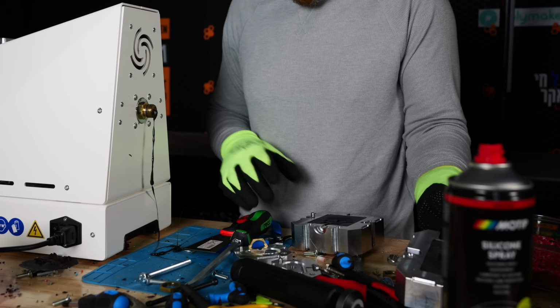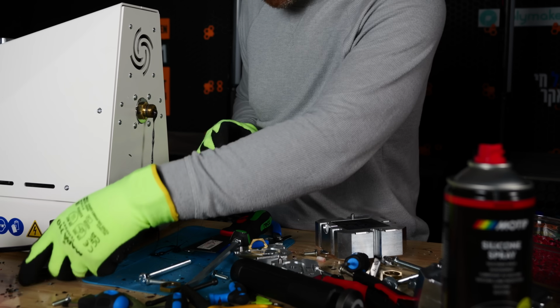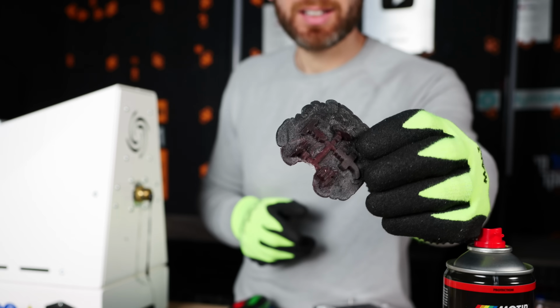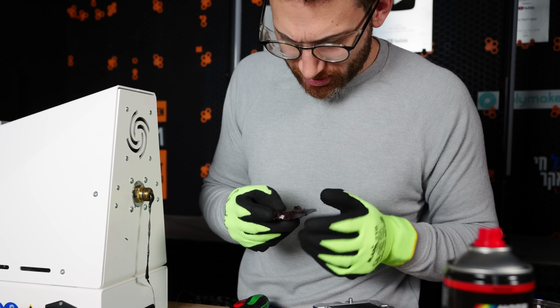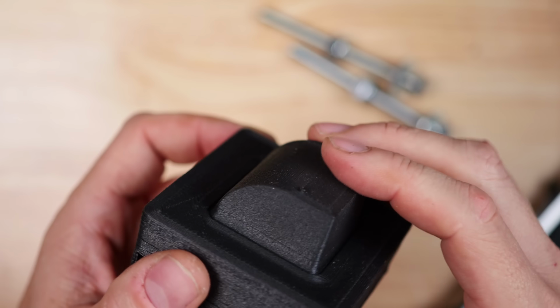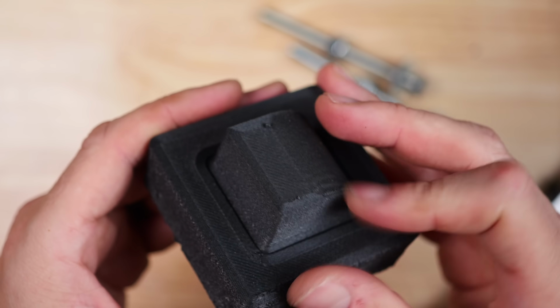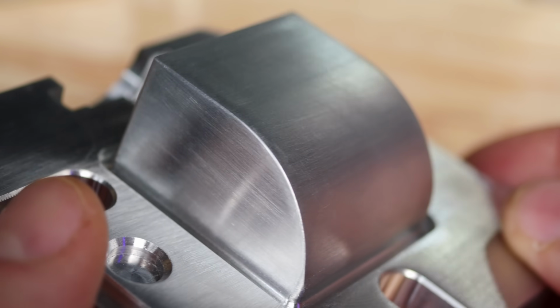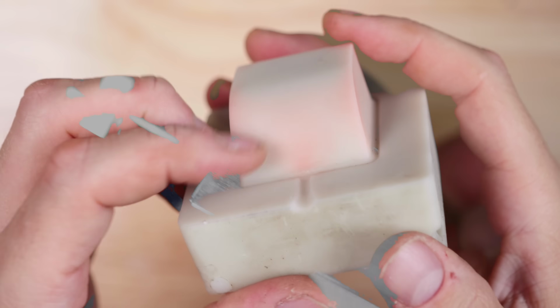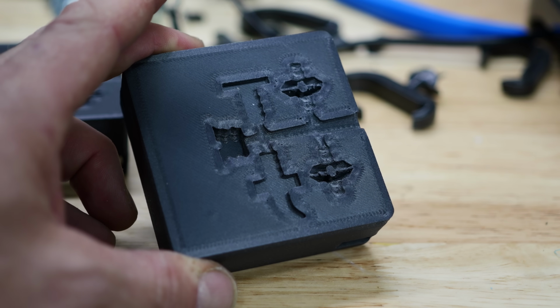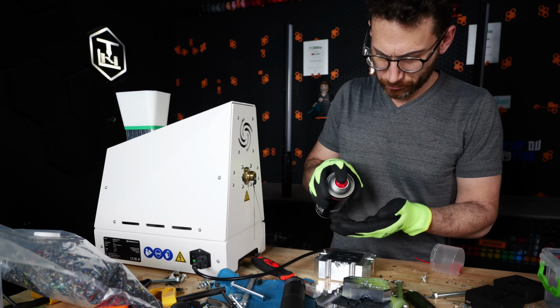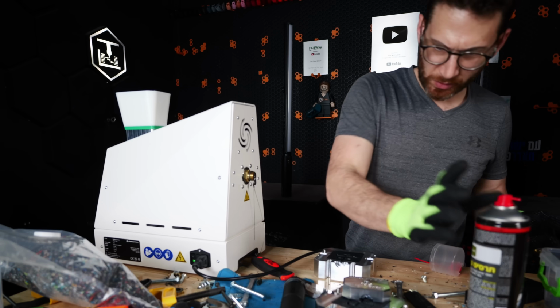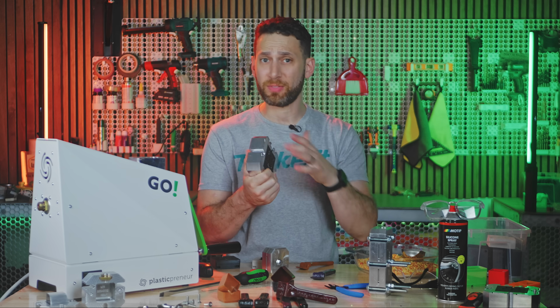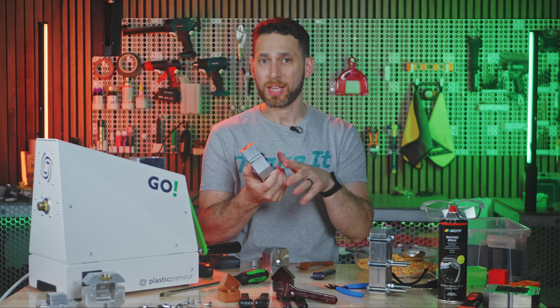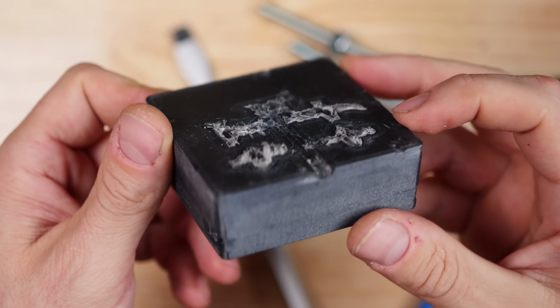There it is. No, we need thicker molds, but that's progress. That's some progress. I chalk this up to the fact that the surfaces are definitely not nearly as smooth as the RA 1.6 of machined aluminum, even in the case of the resin prints. Plus, with these carbon fiber filled filaments, I found that the very necessary silicone spray just seeped into the print itself, leaving none on the actual mating surface, which then caused the parts to bond to it.